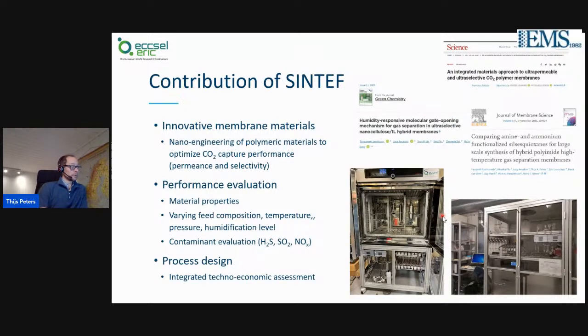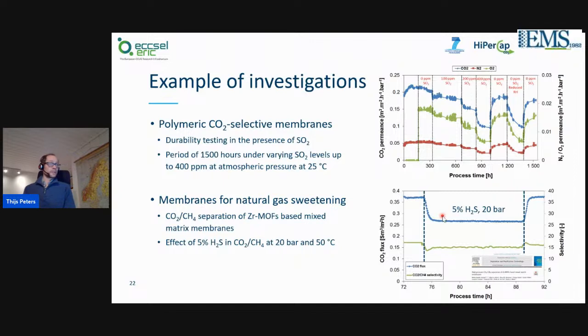And we also have people that work on process design and work on integrated techno-economic assessment of membrane integrated processes. These are some examples of different investigations that we have performed over the last couple of years. For example, for polymeric CO2 selective membranes, we have investigated the durability of them while they're being exposed to different levels of SO2, which is typically a contaminant in flue gas. And within a period of around 1500 hours, we have systematically varied the amount of SO2 between 100 and 400 ppm within the synthetic flue gas, which is being fed to the membrane process.